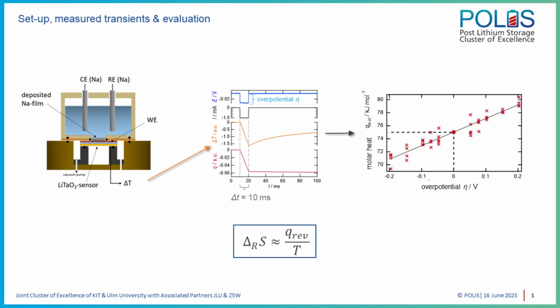And in addition to the potential transients, the corresponding current and the temperature change at the working electrode were recorded. By the thermal response of the sensor, it is then possible to determine the evolved total heat at the working electrode during every pulse. And by measuring the heat evolution during the potential pulse with different amplitudes, we can then rule out the irreversible heat contributions to the measured total heat by plotting the different values of the heat against the corresponding overpotential, and then interpolating to the value for zero overpotential. At this point, the total heat corresponds to the reversibly exchanged heat. And this quantity in turn corresponds to the change in the entropy during the deposition process.